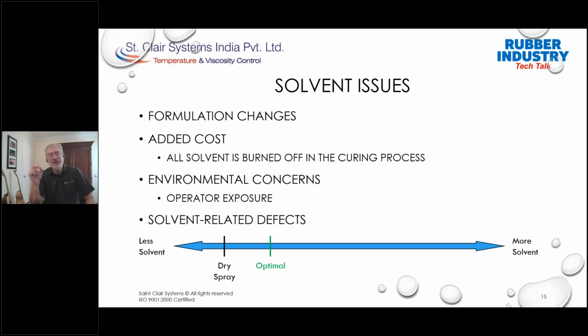But if we continue to add solvent, we begin to get issues with cure, which, as we add more and more solvent, can progress into problems with adhesion and blistering, and as we add more solvent, even solvent pop. This is why the temperature factor is so important.